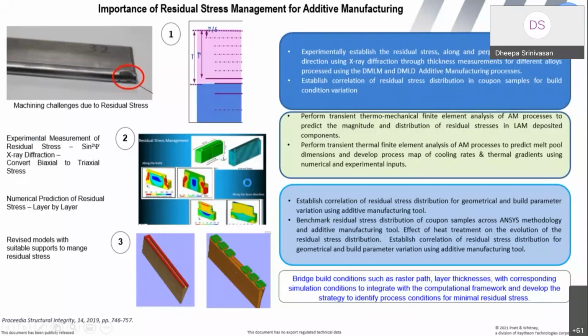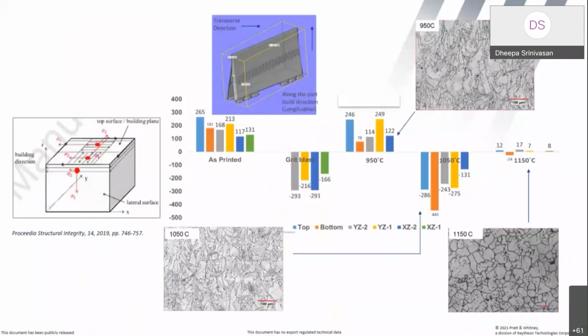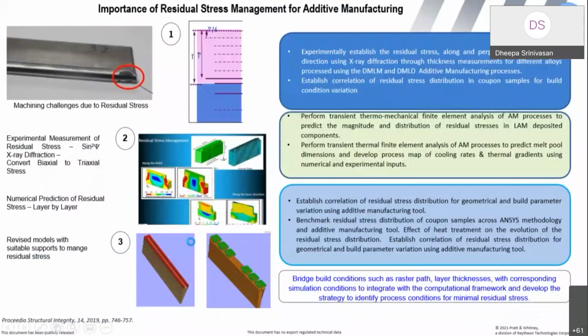And this was a collaboration with one of the NITs, actually. Then we came up with an idea: establish correlation of residual stress distribution for geometric and build parameter, and validate using the additive manufacturing tool. With this, we put in another set of struts. We said we will add a few more, so that we are able to remove 10 or 12 or 15 parts from the build plate without having to face the difficulties shown in this particular picture.